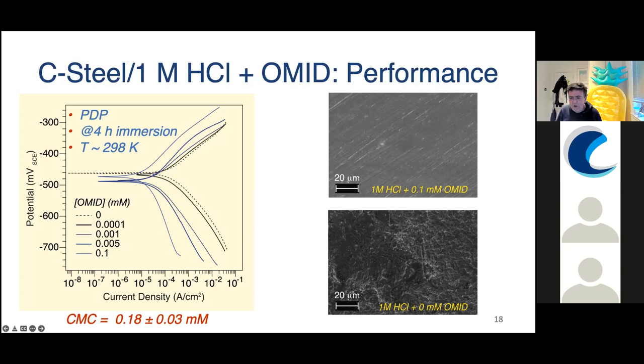Qualitatively, what happens? Without the inhibitor, this is after 4 hours in one molar hydrochloric acid, you can see a roughened surface. This is an SEM image, 20 micron. You can see a roughened surface, there's no localized corrosion, just general roughening of the surface. But in the presence of near CMC, so 0.1 millimolar OMID, you can see it's a much flatter surface. And these lines, actually, you see there's very slight etching, but they're essentially polished marks, and the polished surface would look very similar. So qualitatively, we are inhibiting and reducing the corrosion rate. And in fact, if you looked at this surface optically, it would just look like a polished surface before we'd started.